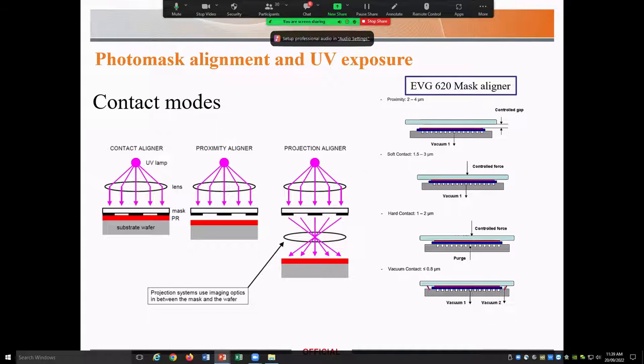Proximity mode is quite similar to contact mode, except that a small gap is maintained between the photomask and wafer. This minimizes the mask damage. Also, it can relatively give us good resolution. In projection exposure, an image of the pattern from the mask will be transferred to the substrate.